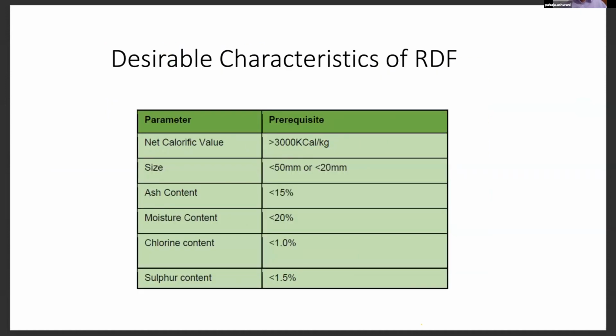So the desirable characteristics of RDF from the point of view of proper utilization by the cement industry are that calorific value should be more than 3000 kilocalories per kg. Size should preferably be less than 50 millimeter for firing into the kiln. And if we have to use enhanced quantities and fire inside the rotary kiln main burner, then it should be less than 20 millimeter. The ash content should preferably be lower than 15%. Moisture content again lower than 20%. Chlorine less than 1%, and sulfur also less than 1.5%. These are the desirable properties.